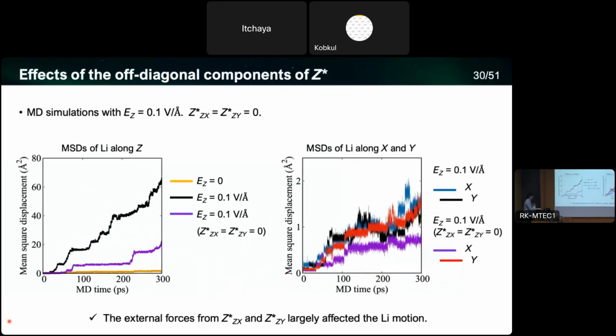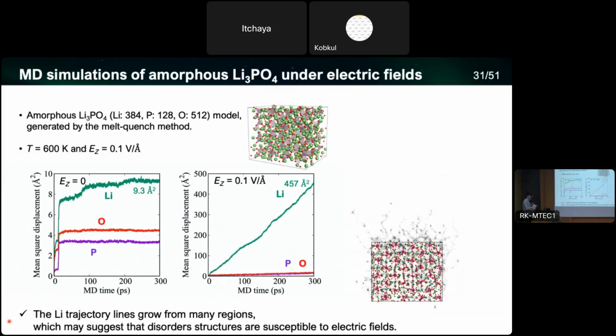So this is suggesting that these off-diagonal components, which give the external forces perpendicular to the electric field, are also important for the lithium motion, which is partly because, as you remember, the lithium migration path is not completely direct along the z direction, but partly going right and going back to the left. So this off-diagonal component has great influence on the lithium motions. That is the interesting point, I think.